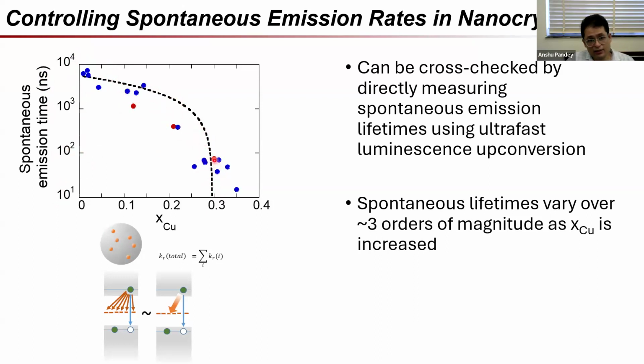The second thing is we can again re-verify that as the copper amount increases, the sample is indeed getting faster in its emission by again using the same old trick which I mentioned earlier, which is to check whether it's getting brighter and brighter in UPL. The answer is it does get much brighter in UPL. And this tells us that the spontaneous lifetime is in fact shortening significantly.